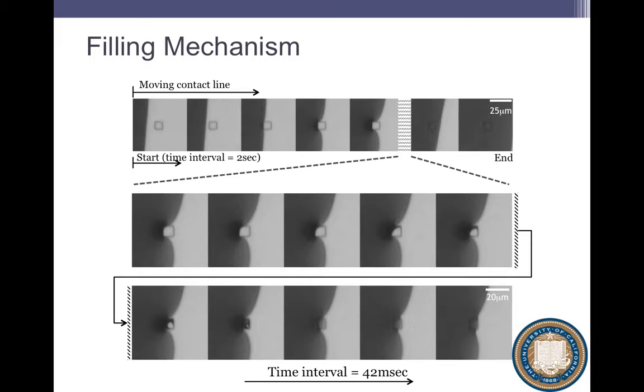But let's say I go too fast. Let's say I'm printing or filling too fast. What happens is the top, in other words, this front over the top, covers the cylinder before I have expelled the air. And that turns out to be something we've observed. We've actually observed it experimentally. There's something called air entrapment that happens, and you get a bubble inside the cylinder. That's bad, because now I didn't fill the cylinder as much as I wanted. My cylinder is maybe only 10% full instead of 100% full. So that's a really big problem.